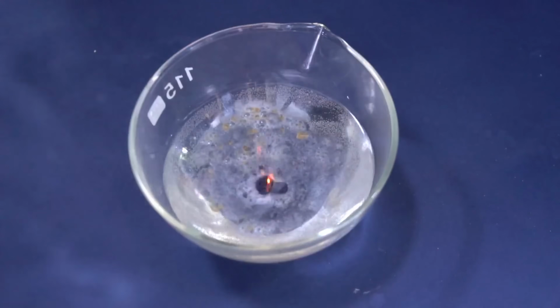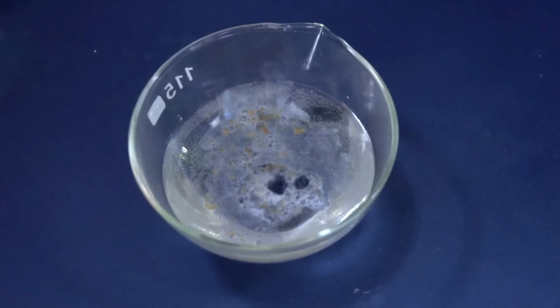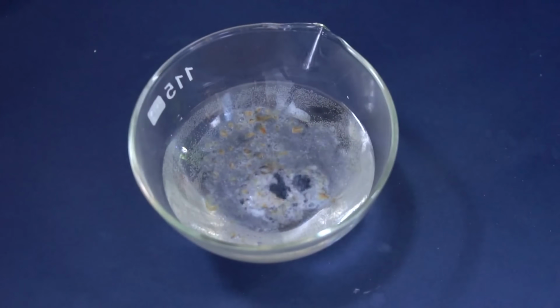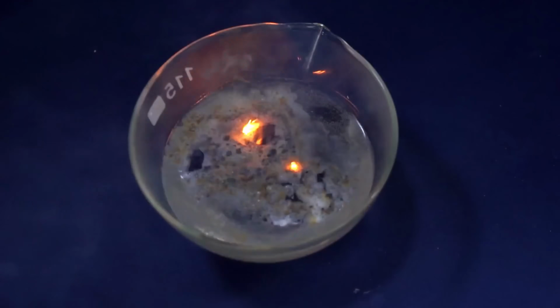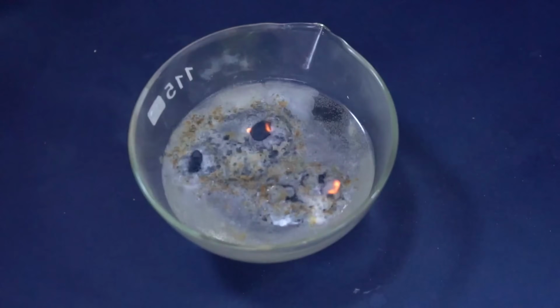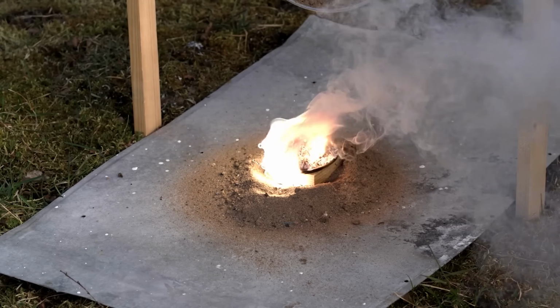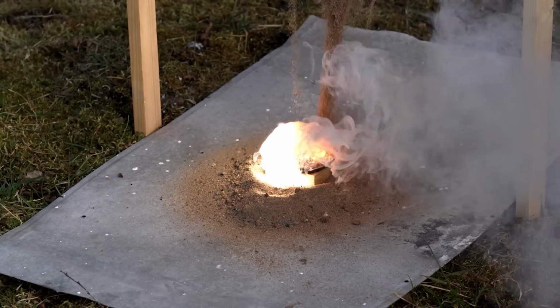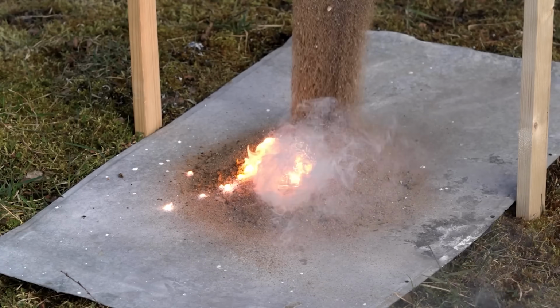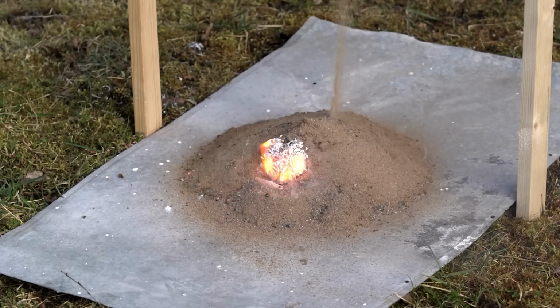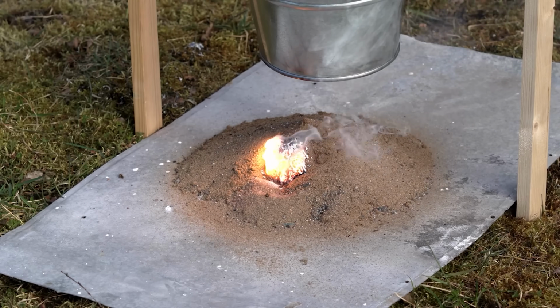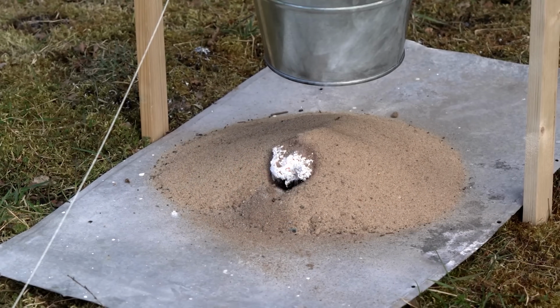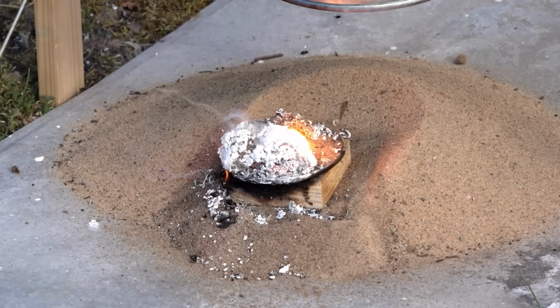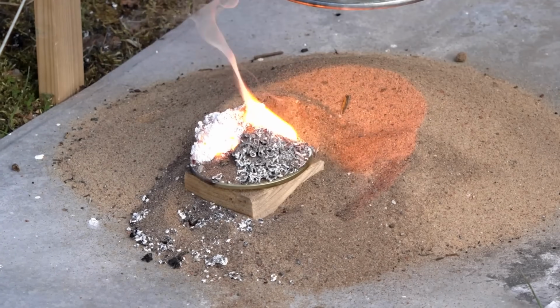Another reason why burning lithium shouldn't be extinguished with sand is silane. It's a flammable gas produced by the reaction of the above-mentioned chemical substances with water. Finally, I decided to see if burning magnesium can be extinguished with sand. Sand partially coped with this task, even though magnesium kept burning. Apparently, the amount of sand just wasn't enough. Using sand to deal with the combustion of magnesium can only make it burn more intensely.